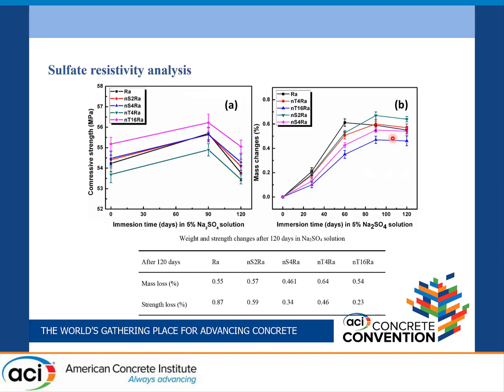For the mass loss, we see 0.55% mass loss after 120 days, and for the titanium and silica 4%, the mass loss is 0.461% and 0.54%. So what will happen?